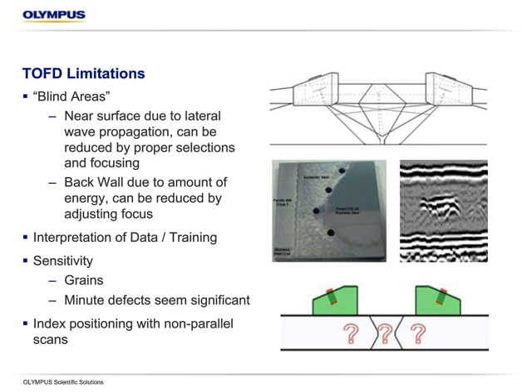Also the sensitivity. TOFD is very, very sensitive. If we can diffract a flaw and pick it up, it typically will pick up even small grains or negligible flaws. So people see this as a downfall because when you look at the data, if you have a large grain material like austenitic or a casting, some other ones that have very large grains compared to carbon steel, especially, it can show a lot of different things that may not be critical or may not be a detriment or a discontinuity to the actual piece.